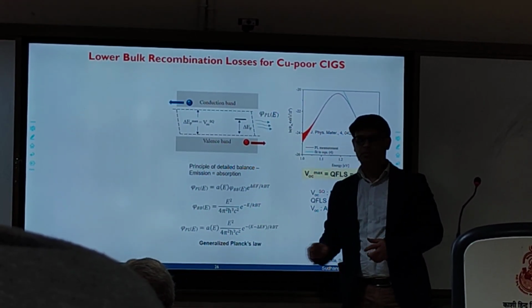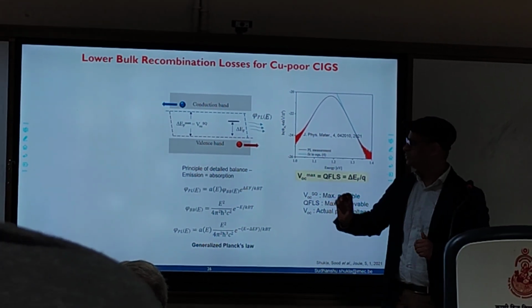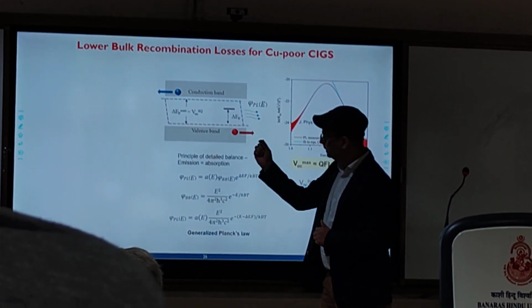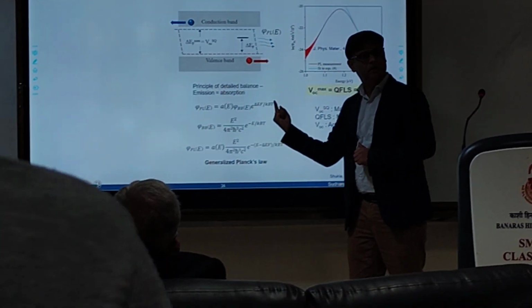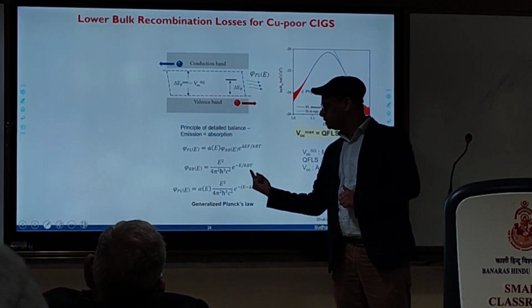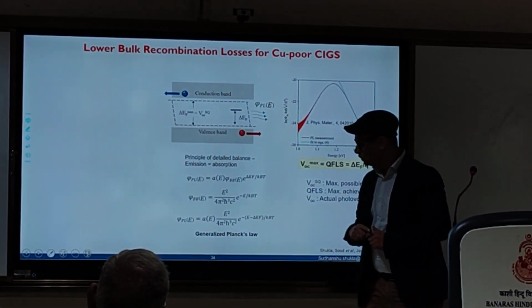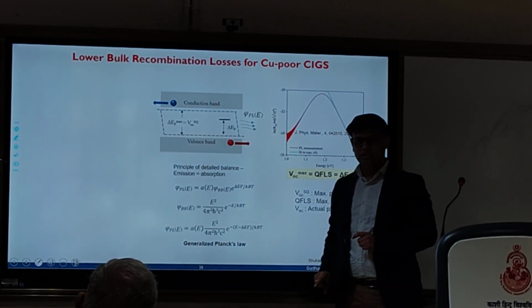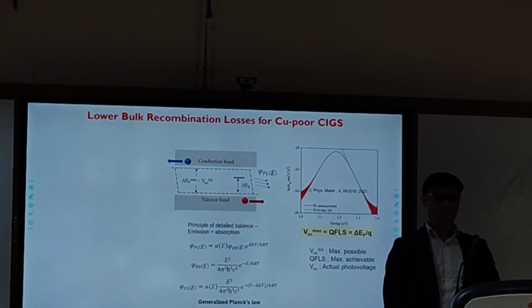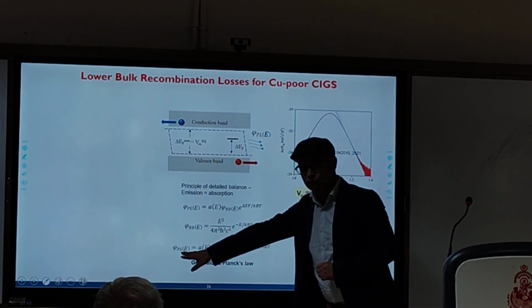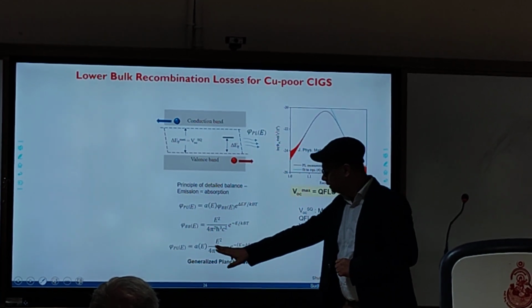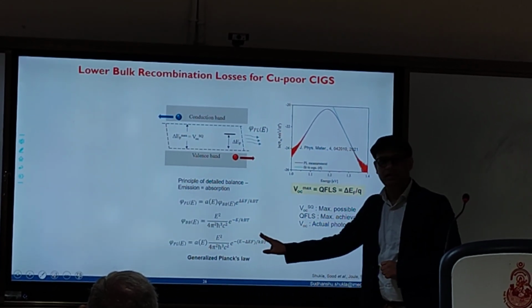So this non-equilibrium is essentially when you shine light, you generate this delta EF split. This is the non-equilibrium factor. Black body, you already know, this is the relation, this is Planck's law, and then you plug everything in that, it becomes a generalized Planck law. So with this, if you know the photon flux coming out, PL, you can actually estimate the delta EF, which is the quasi-Fermi level splitting.